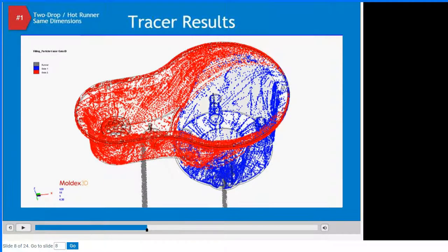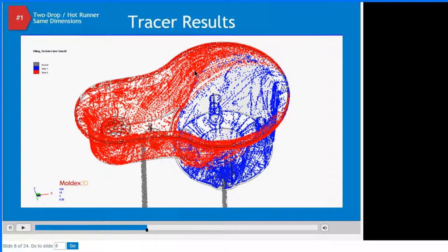When one section is filled from its hot runner drop, the flow keeps going through both gates, but this material flow can now only go to the right side of the part. The flow energy has shifted from the gate towards the right. This elongates the molecular chains towards the right, aligns the molecules and fibers to the right, increases shear rate to the right, and raises temperatures to the right. The entire flow behavior changes if these two geometry sections — small left and large right — are not filled equally. It's a challenge.